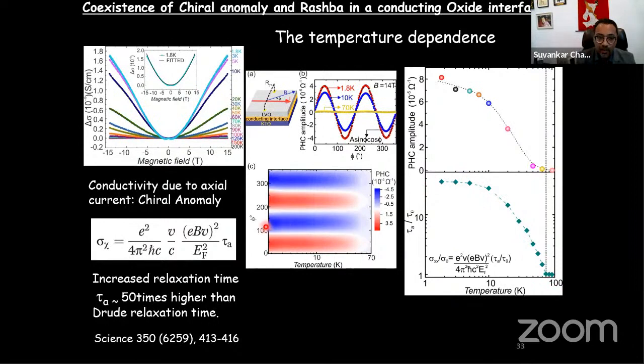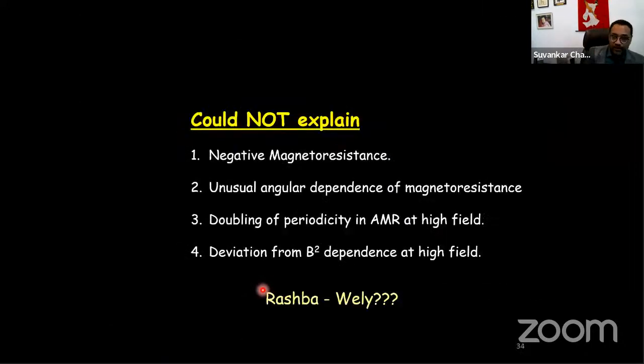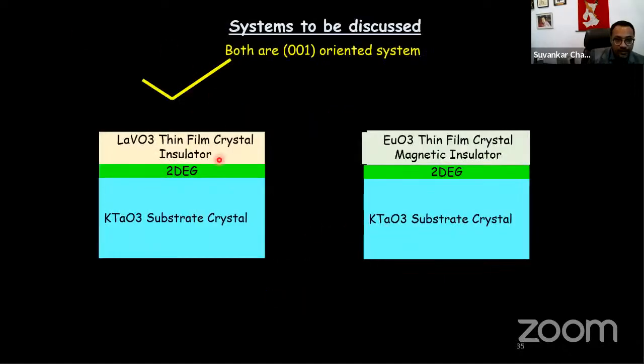And our planar Hall effect also vanishes around 70 Kelvin, which suggests that the planar Hall effect and this appearance of axial relaxation time or axial current have some intercorrelation with each other. So our model could not explain the appearance of negative magnetoresistance, then the unusual angular dependence, which is different from Weyl type behavior, and the doubling of periodicity of this anisotropic magnetoresistance. So I have completed this part, and I don't think I have time.